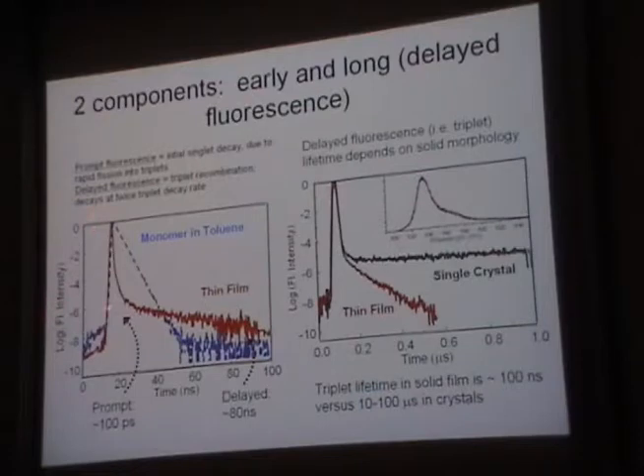When you put it in a thin film, you see the textbook delayed fluorescence: fast decay, and then you see this long component out here. So again, we seem to have this signature of exciton fission, or at least triplets recombining, right? Beautiful single exponential for the monomer in toluene. There's no funny business going on in tetracene by itself.